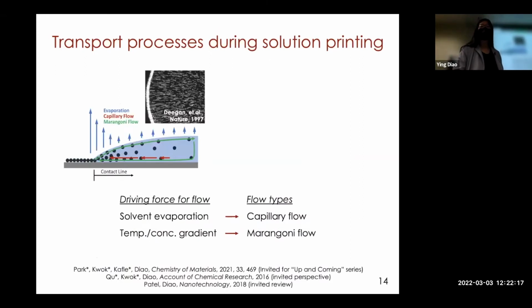To get a little bit technical, it's really fascinating to look at the transport processes during solution printing. For a drying drop problem, the physics was figured out through the coffee ring phenomenon back in 1997. If you drop coffee on the table, you will see a ring formed after the droplet dries. That's because there's an uneven evaporation profile modulated by the curvature of the ink-air interface.